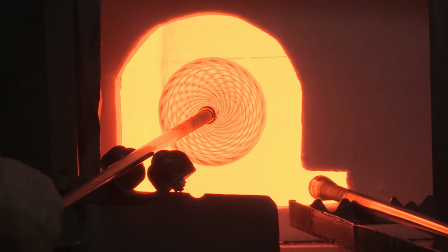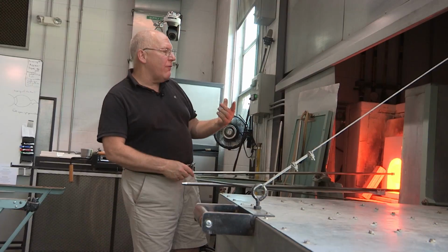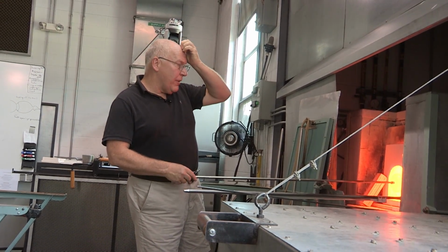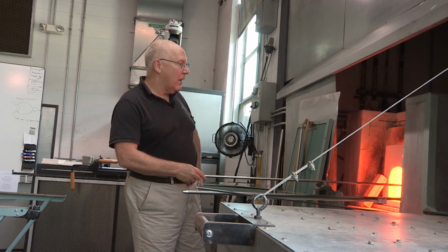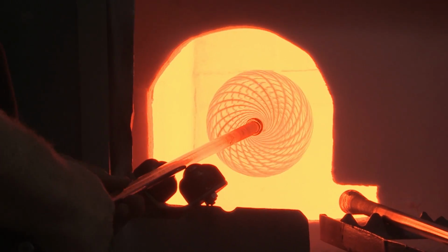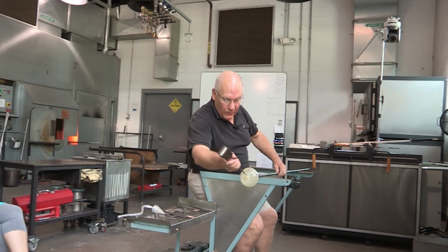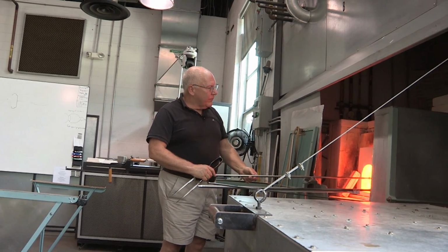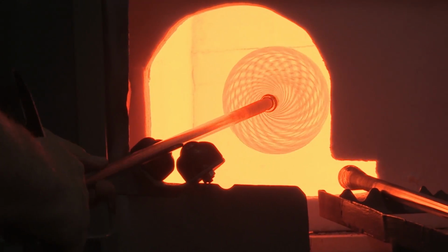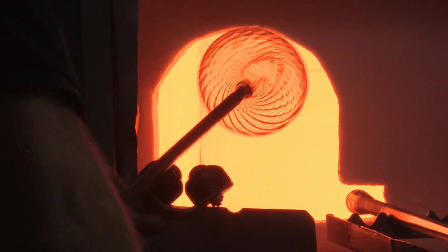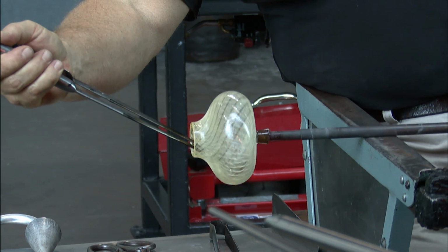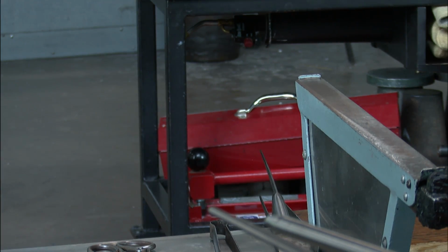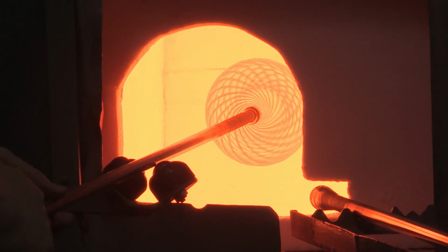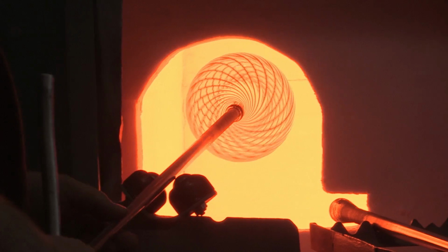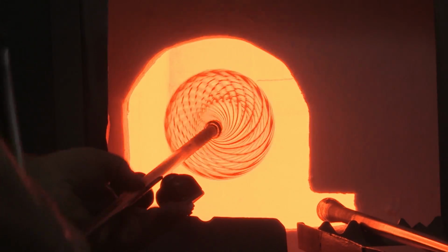What I'm doing is my first reheat after the transfer to the punty. Like I said before, I can only use the Soffietta once because it's a low shape. And to make it count, I'm going to open the hole to about 1.5 inches in diameter. You saw the inner fold before. Here I'll do an outer fold. I use the Soffietta to make it a little bigger.